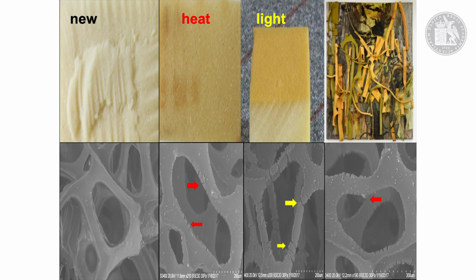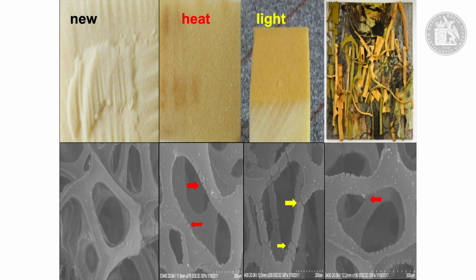And what we can see here is that the new foam, at around 200 times magnification, the cells are in good condition. When you do heat aging, they're slightly degraded. With light aging, they're extremely degraded, and the foam has developed into crumbs. It's just fragmented. When we look at a sample of the real object, it's much more similar to light aging than heat aging. So we know that we've done some overkill with the accelerated aging.